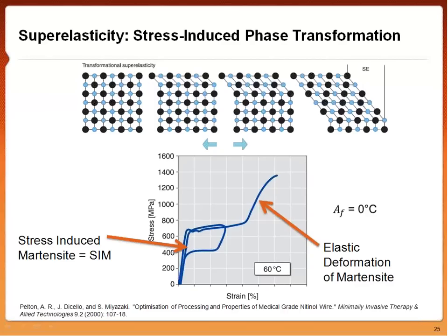We have the initial up to about 1% elastic pulling of parent austenite, and then we reach a plateau, just like we saw in that martensite phase. We reach a plateau because we are stress-inducing martensite, we are stress-inducing a phase transformation. Finally, we reach a peak where we can no longer stress-induce phase transformation, and we have elastic pulling of that detwin martensite. So it's going through the same mechanisms, okay? And the phenomenon is really linked through thermodynamics.